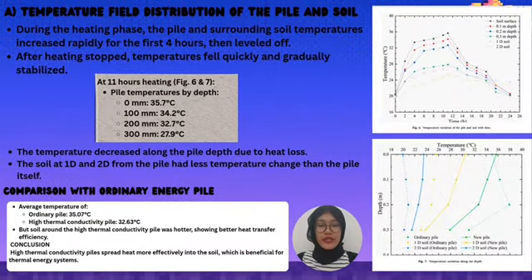Temperature field distribution. During the first thermal cycle, both the pile and the surrounding soil temperature rose quickly within the first 4 hours, then stabilized. The pile temperature decreased with depth, measuring 35.7 degrees Celsius at the top and only 27.9 degrees at the bottom. Compared to an ordinary concrete pile, the high thermal conductivity pile shows lower internal temperature; the pile transfers more heat to the surrounding soil. This demonstrates the enhanced pile spreads heat more efficiently, reducing internal heat accumulation.